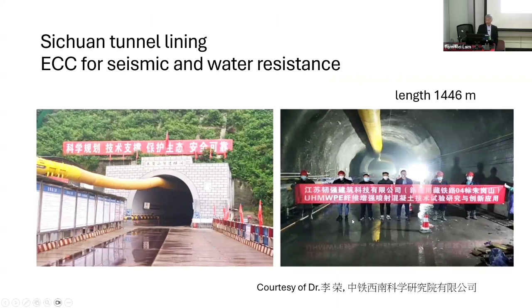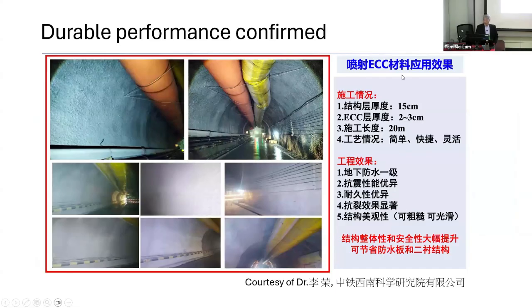This is another application much closer to now. It's a couple of years ago, I believe, and it's carried out in Sichuan in China. So I ran into Dr. Li Rong a couple of months ago, and he showed me these images he took. This is a use of ECC, again by shotcreting ECC as a tunnel lining. And what he was pointing out after a few years of experience is that this ECC tunnel lining remains watertight. It demonstrates high resiliency against earthquakes, and durability and crack control, and even control of the surface finish, which they like to have. So these are some advantages, and the reports after a few years of use remain very good.